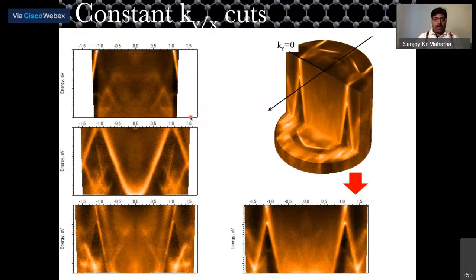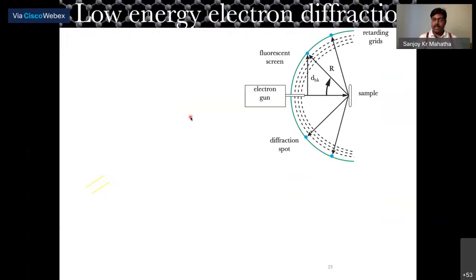Good. So now let me tell you something about low energy electron diffraction. It is a technique where we shine the material surface with a monoenergetic electron beam. And then the backscattered electrons are collected on a fluorescent screen, okay? And by seeing the spot profile or the symmetry of the spots, we can try to understand what the structure of the material is and how clean the surface is.